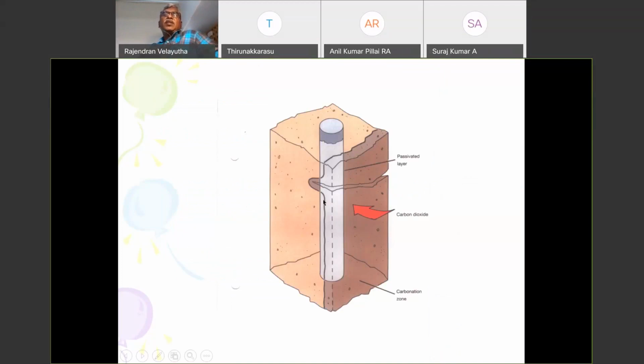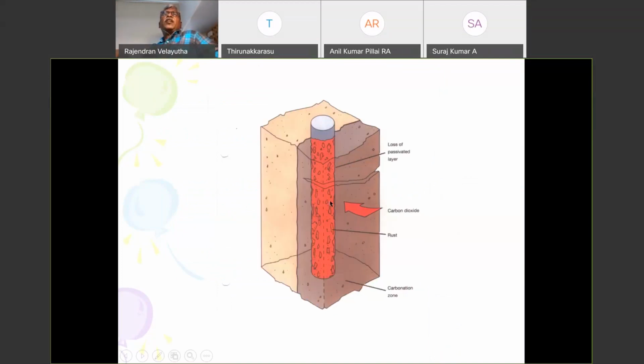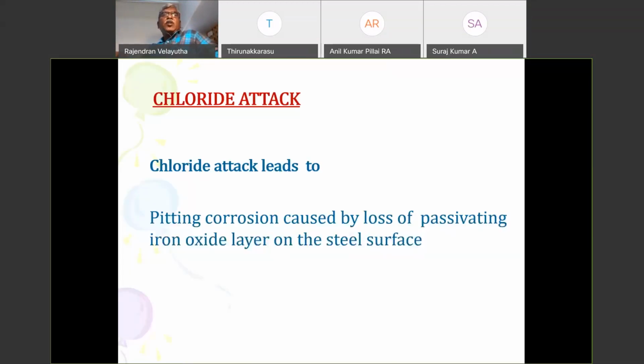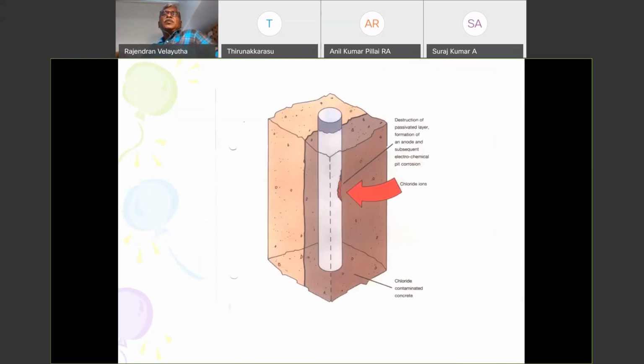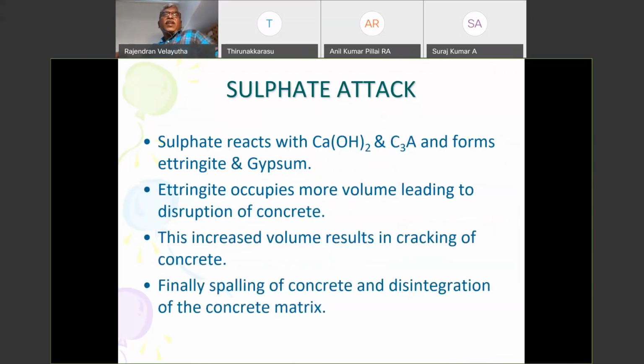The moment the carbonation level reaches the reinforcement, you get corrosion, and this corrosion is always uniform corrosion. With respect to chloride, pitting corrosion is the most dangerous one, because the chloride ions go in and form pits, and this makes a discontinuity in the rebar. Obviously, the structure is going to fail all of a sudden without much warning, and that is an issue.